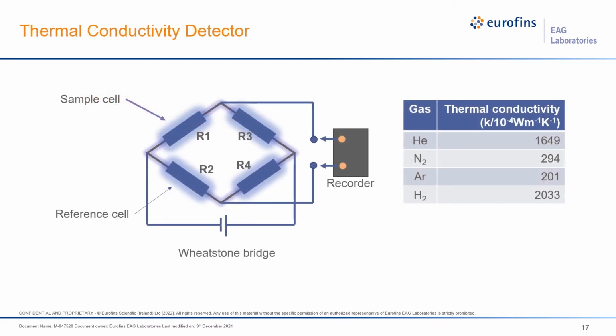The other method is based on detecting thermal conductivity difference using a Wheatstone bridge arrangement. Thermal conductivities of the reference gas, usually a carrier gas, and the sample gas are compared to determine the concentration of the sample gas. It is therefore necessary to have very different thermal conductivities for the sample versus the reference gas. For example, to detect nitrogen, helium carrier gas is suitable, whereas for hydrogen, argon should be used.